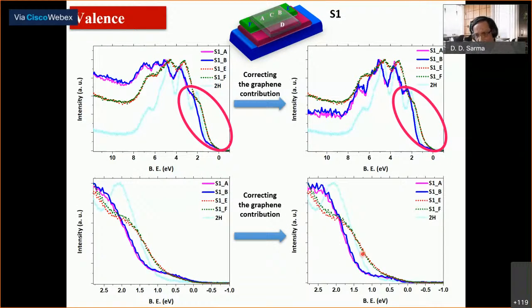It turns out that even in the valence band, this is the part which is not from the heterostructure. This is the part from the heterostructure, and that also is separated by approximately 0.4, 0.5 electron volt. So basically, it is a question of referencing of the energy. As we know, photoemission always references to the local Fermi energy.